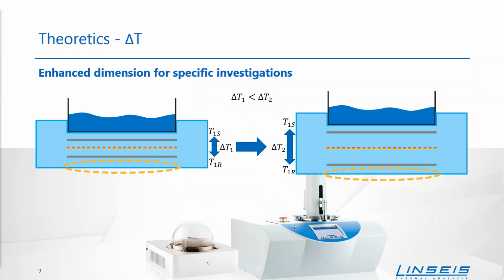And with the magic called calibration, we can say this is, for example, 10 joule per gram or something like this. And as you can see with the bigger layout, we have a higher temperature gradient because the heat between the sample and the reference sensor is much bigger. So this is the theory of the delta T. And this is what we want to reach, and we can perform this.